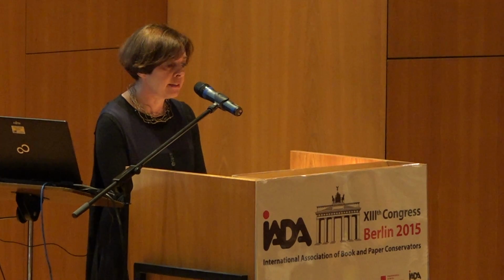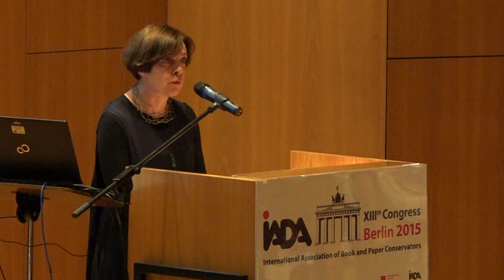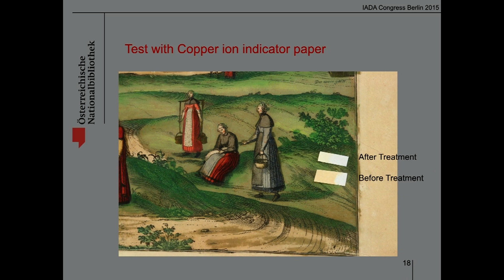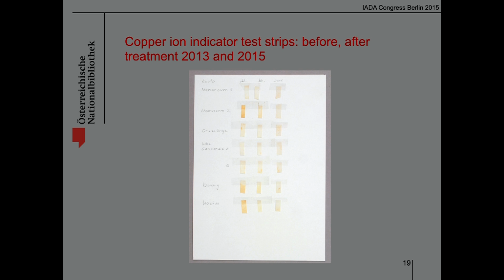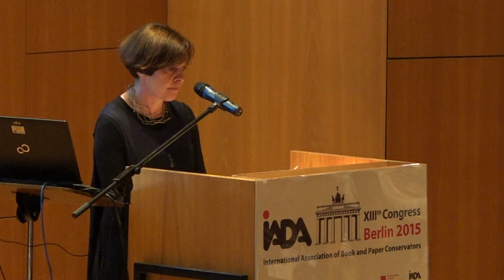In the slide you see the indicator paper on the detail of Danzig before and after treatment. The indicator papers were used to monitor conditions 2 years after the treatment. The reaction was similar to the test in 2013. According to the indicator papers, the complexing reaction seems to be stable.